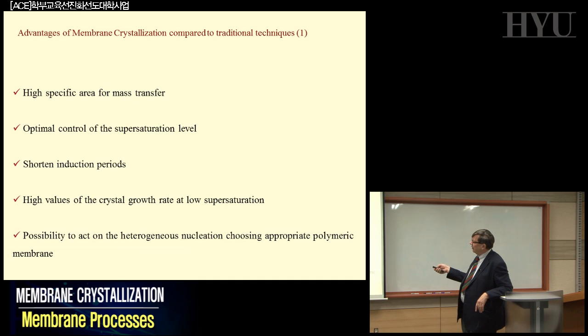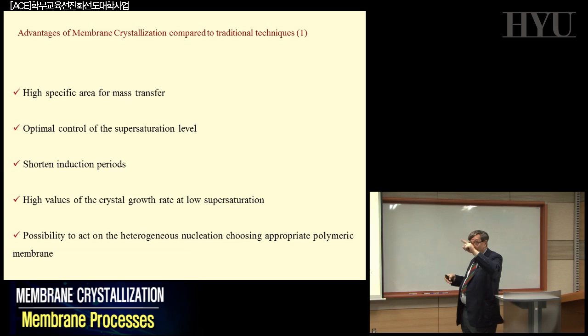But anyway, the advantages of this crystallizer, from the one we mentioned before, are that we are able to realize very high specific area for mass transfer. Putting a lot of fibers in your module, you have very high surface available for each one of the pores we are discussing. You can have an optimal control of the supersaturation level, as we have been discussing. As a consequence, we will have a shorter induction period, high crystal growth at low supersaturation, and the possibility to act as a heterogeneous nucleation if you change the chemistry of the polymeric material that you have, the surface energy of the system.